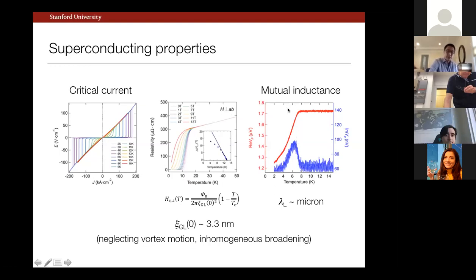And finally, by doing a two-coil measurement, we looked at the mutual inductance. And what you can see here is the onset of global superconductivity, and then you can see the screening response of the sample between the two coils. And we're probably still at a very cautious stage of trying to give you hard numbers. But let's just say with the variations available for order parameter symmetry or the scale of relevant disorder, whatever else is true, the London penetration depth will be on the scale of a micron or so. So it's a very extreme type 2 superconductor.